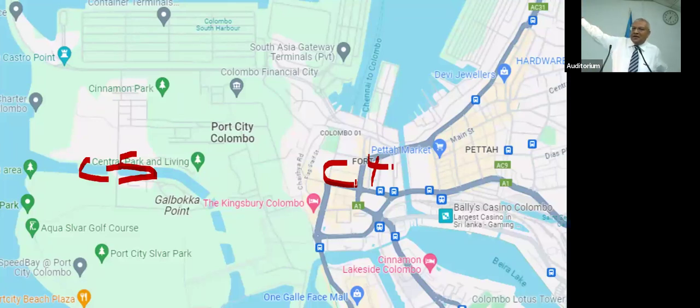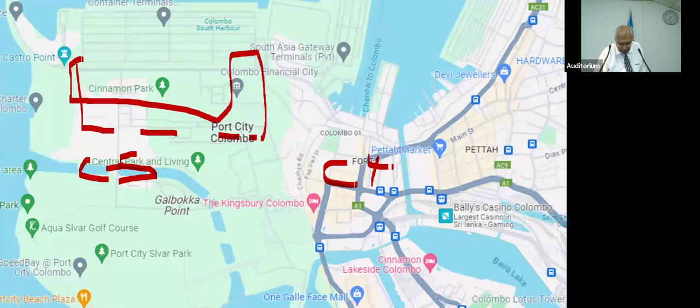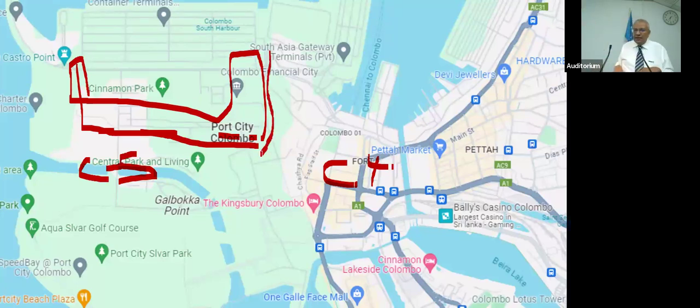So, environmental modification, I mean, it can happen every day. But there are things like this. Now, for instance, you take a sea channel. Okay. Now, according to the ISO, you have to put 280 microns. So what you do is you put 280 microns on all sides. Then the water will fill up during the rain. Then if you look at the chart, it is called IM1. Below the chart, there's a thing called C1, C2, C3, C4, C5, IM1, IM2, IM3. IM1 means freshwater immersion. IM2 means seawater immersion. So now you all have had a building with a sea channel facing upside. Then the rain came, it filled up. Then that is not C5M, it is IM1 now.